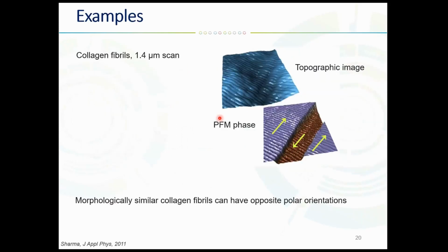So where can we use it? Piezoelectricity is a potential that is induced by mechanical stress in crystalline or structured materials. Many years ago, different piezoelectric effects were demonstrated in bone and lung and so on. Here is an example of collagen fibrils. When we use piezoelectric force microscopy, we can see the different directions of these fibrils, even though on the topographic image we don't see much here. When you apply these forces to the samples, what you can see is the change of the direction of the fibrils.